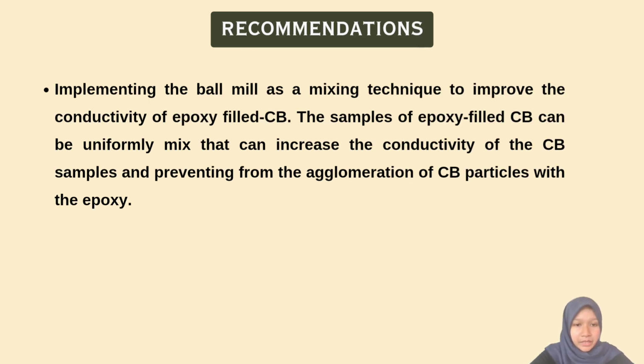For the recommendation, the study can be improved by implementing the ball mill as a mixing technique to replace the sonicator technique, which is to improve the conductivity of epoxy-filled carbon black. The sample of epoxy-filled carbon black can be uniformly mixed using the ball mill, which can increase the conductivity of the carbon black sample and also prevent the agglomeration of particles with the epoxy.